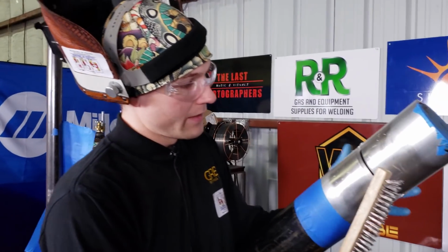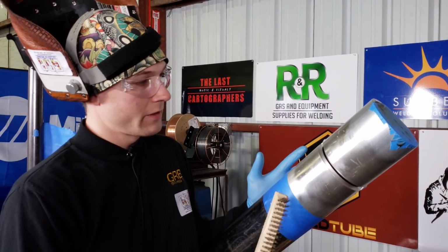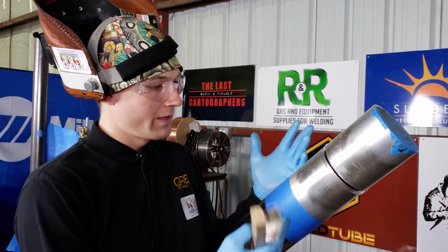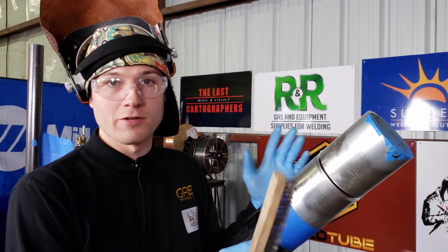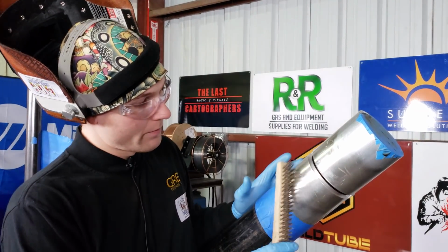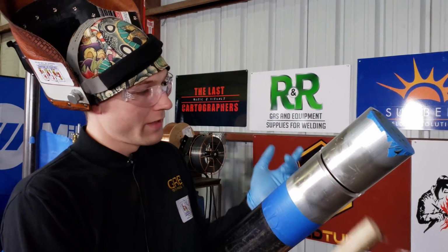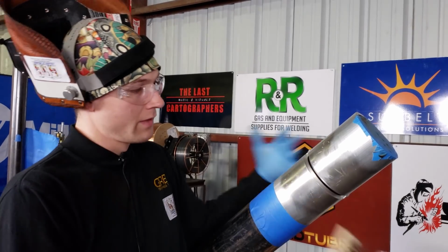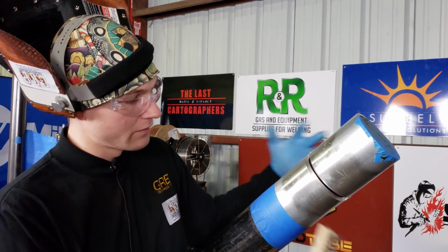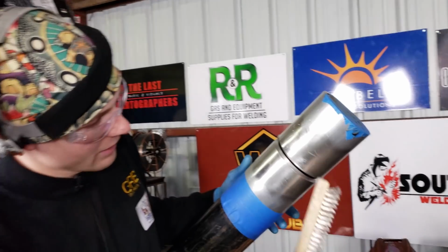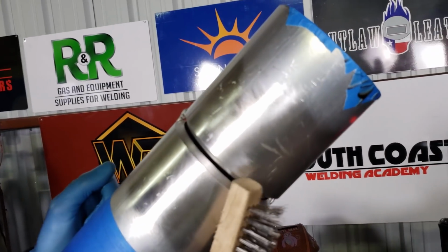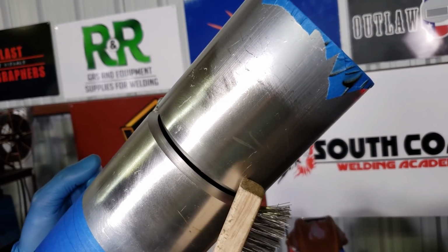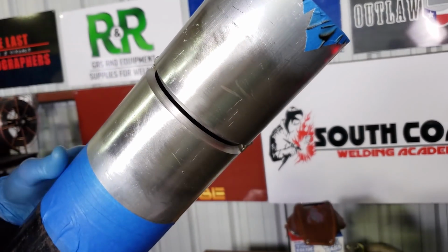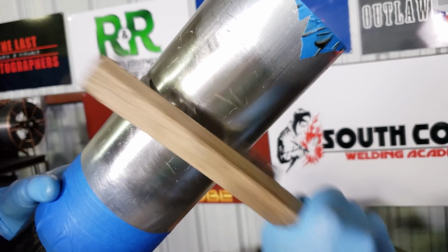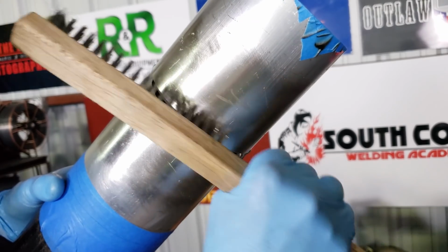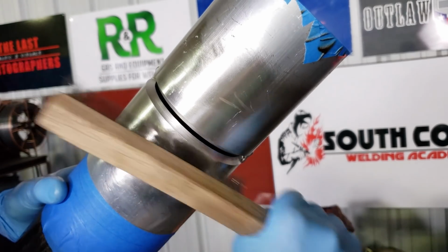Okay, so essentially we just preheated the pipe up to 250 degrees Fahrenheit. The reason I went with 250 Fahrenheit is because it's hot, but it's not going to scald my hands. I'm brushing the oxides off, and the oxides do remove a lot easier when the material is hot, but even at this temperature it's rapidly forming oxides really quickly. If you look at the pipe here, you can tell exactly where I brushed, mostly down here. Oxides are coming off now. Same with over here.